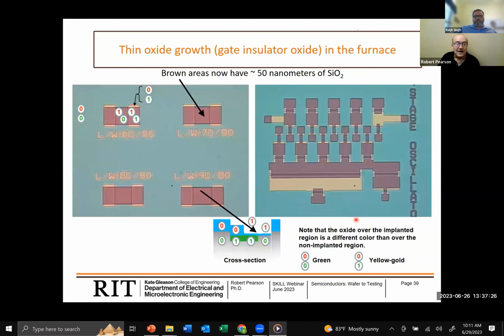And this is after we've etched the oxide down to the bare silicon, because this is where we're going to grow the very thin oxide for our transistor. The inset picture here is showing something called an alignment vernier, and this is checking to see whether or not we're off in the Y direction. And it turns out that we've got really good Y alignment. All right, now we've grown this thin oxide here, and that's the brown regions. And this shows individual transistors of various lengths and widths. And this shows this oscillator circuit coming together very nicely.